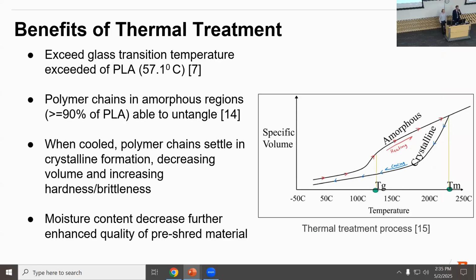And what we wanted to do was essentially heat it up well above the glass transition temperature of PLA. Now, when we do this, the amorphous regions of PLA, which is the majority of PLA, typically around 90% of PLA is amorphous, allow the polymer chains to untangle, and then upon cooling, as you can see in the graph, it becomes more solidified in a crystalline manner. And that decreases the specific volume and consequently increases the hardness and brittleness. At the same time, it also lowers the moisture content, which, as we discussed earlier, is something you want to try to do.